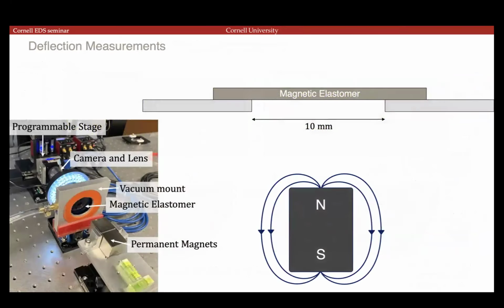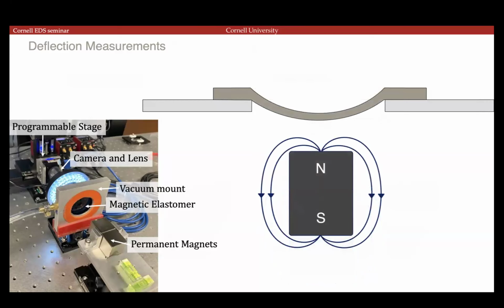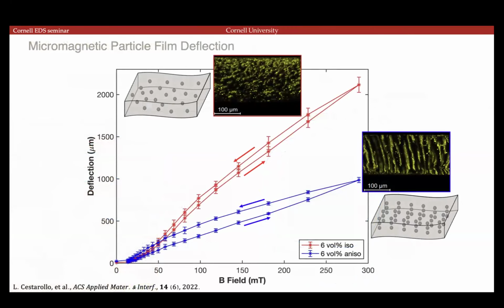The actual deflection comparison comes from a setup that we built in the lab. If we mount our magnetic material on this surface and then apply a magnetic field just by moving the magnet closer, the film will deflect and we can focus on the surface to determine the amount of deflection achieved. What's being applied here is actually the magnetic field gradient. As I said, the force is related to the gradient, but a lot of times it's easier to discuss just the field. So here we plot the comparison of isotropic versus anisotropic deflection.